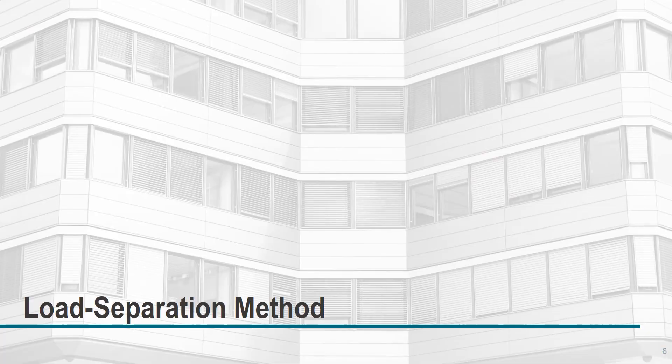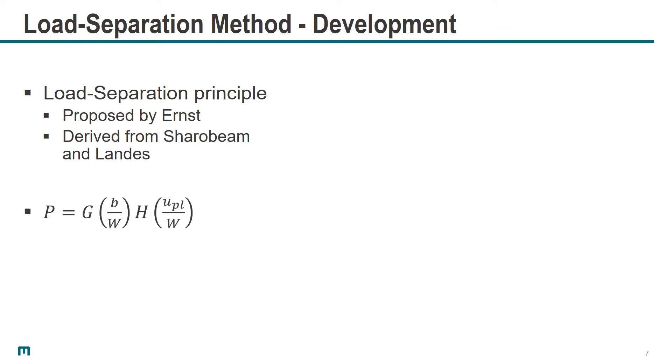One method that aims to do so is the load separation method, based on the load separation principle first proposed by Ernst and later developed by Sharobeam and Landes. The load separation principle states that as long as you have the same material, geometry, and constraint level, you can split the force P recorded in a fracture mechanics test into two independent functions: G, the geometry function, and H, the deformation function.